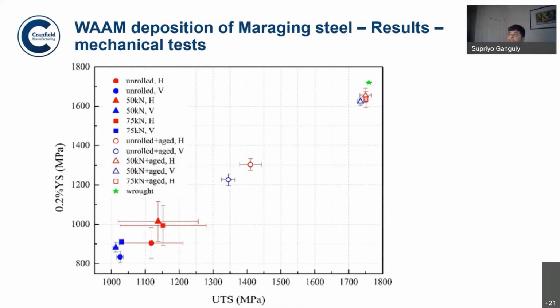Now you can see here the unrolled horizontal and unrolled vertical, shown by the red and the blue marks. I will take these triangular ones, so 50 kilonewton aged, horizontal and vertical. It has now achieved the level of the wrought alloy, which is shown by the green star. The empty circles, the red and the blue, are the as-deposited and aged ones. So what I'm trying to convey is that cold rolling is an extremely important tool to allow the matrix to be solutionized properly, and therefore its aging response increases tremendously.